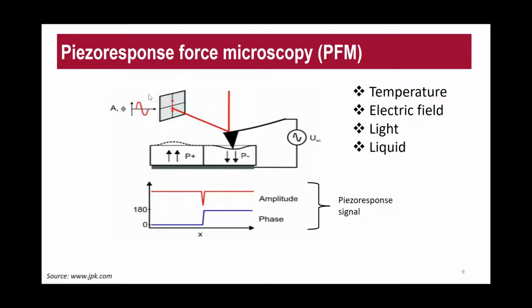In this PFM setup, which is a very simple one, it shows an AC voltage that can be applied between a tip and a sample. Of course, the tip has to be conductive. When you are using a PFM measurement, you need to select a conductive tip. Having a conductive tip, it will act as a movable top electrode that couples to the material surface.